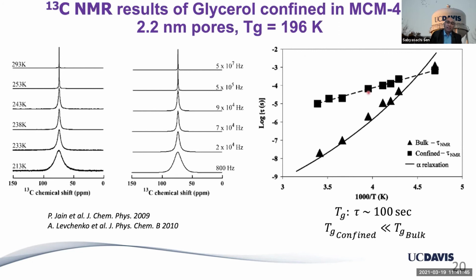So NMR says the TG has to be very low if we take the tumbling process or isotropic rotation process of the molecule. But then the DSC, differential scanning calorimetry, says otherwise. So the only way to explain the discrepancy is to say that the glycerol under confinement is a different liquid compared to under bulk, so that the actual alpha relaxation or the primary relaxation is something that must be along this line, which has nothing to do with the single molecule rotation anymore. So this becomes then a beta process, which is diverging from the primary relaxation alpha process in glycerol. So that means there must be a change in the equation of state of glycerol if it's a fundamentally different liquid.